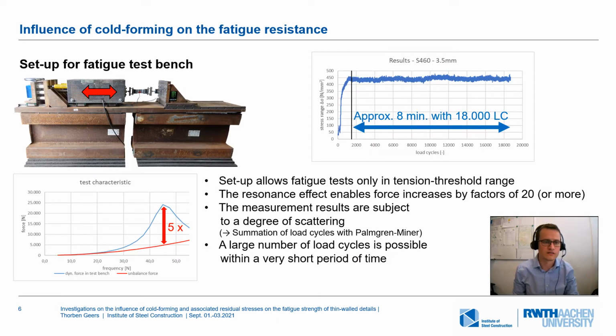Before I present the results of the fatigue strength, I would first like to talk about the specially developed test bench. The monster, that's what we call our test bench, is a resonance test bench. The setup primarily allows for tests in the tensional threshold range only. The advantage, however, is that although the unbalanced exciters in the movable slide in the middle can only generate a maximum force of 6 kN, significantly higher forces with a factor of 5 in this case or more can be generated in the specimen via the resonance effect.